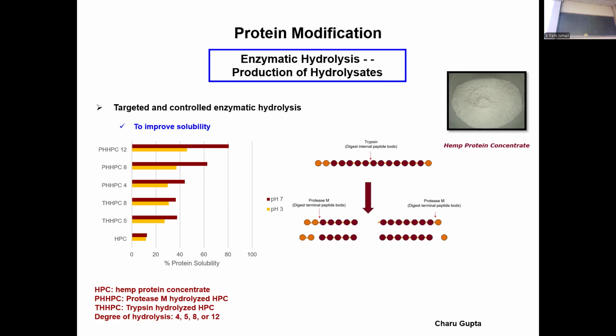Hemp protein is a really very insoluble protein, so when we use this enzyme, all of the enzymatic treatments improved it a little bit because we started with very low solubility. It was a very poor protein to be soluble. All enzymatic treatment enhanced solubility a little bit, but the exoprotease enhanced it the most. What pH? What we do is we measure solubility at 2 pHs: pH 7 to simulate a neutral beverage, and pH 3.4 to simulate an acidic beverage. Whether it's 3.4 or 7, all of the enzymatic treatments were better in solubility than the one that was not treated, because we started with very insoluble protein.